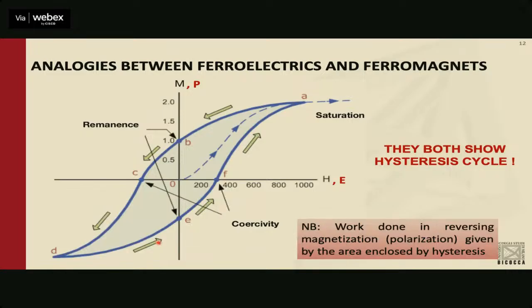Another analogy is that both ferroelectrics and ferromagnets show a kind of hysteresis cycle. So in the M-H phase space, you have a hysteresis loop, the meaning of which is that the area enclosed by this hysteresis cycle tells you the energy stored in a material or involved in the reversal of the order parameter. So there are many analogies, but of course there are many differences, right?